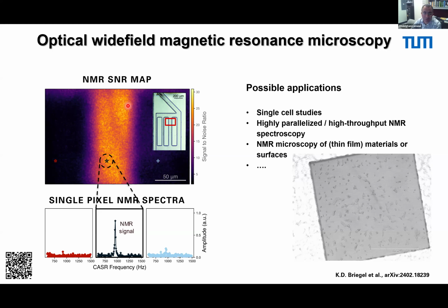Yeah, and then this relates to the CASR pulse sequence. So what limits exactly the line width of this? Well, here it is really our own limitations. I mentioned this quickly before. When we did this experiment, I bought an objective from a special company, for a lot of money, which was supposed to be non-magnetic. When you put it in, there was no NMR signal.